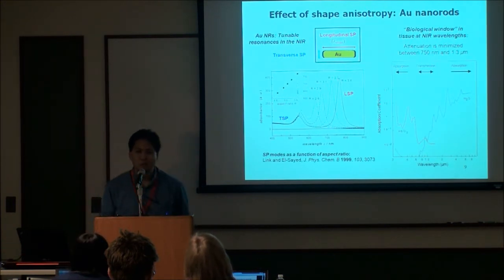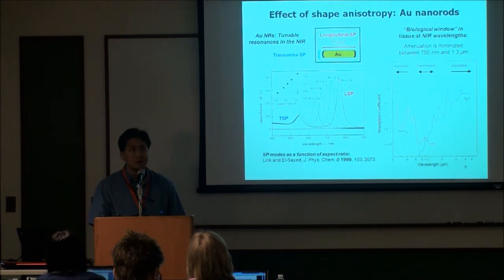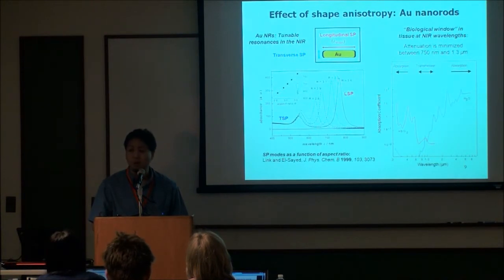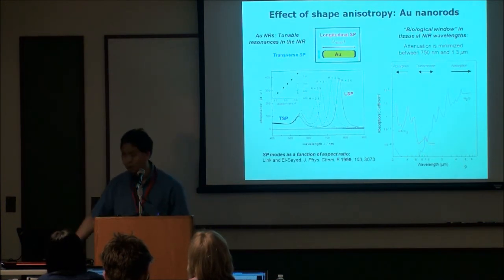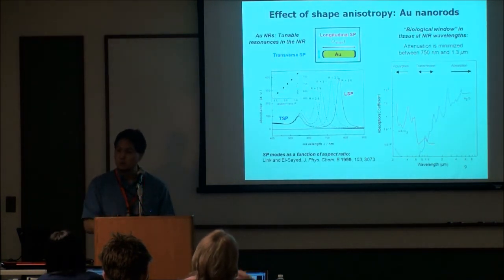Yeah, it's a complex question. The question is whether you can predict how efficient a particle is at producing isotropic scattering or elastic scattering or other modes. For the most part, you can. It would be safe to say that resonance absorption and scattering pretty much takes up 95% or more of the output from any plasmon-resonant nanoparticle. So that's a safe assumption. But there are variations, and the shape of the particle can cause things like depolarization. You can lose phase as a function of the structure. I'll show one example of that later in the talk. But you can presume that nanoparticles do provide a great deal of elastic absorption and scattering.